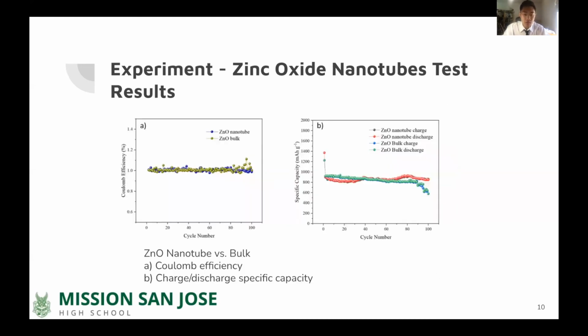Finally, in this figure, the nanotubes are a lot more stable than simple bulk zinc oxide. The bulk zinc oxide specific capacity is higher than the nanotubes for the first few cycles, as you can see in the figure. However, it steadily decreases until around cycle 80, where it starts to drastically decrease. The specific capacity for nanotube zinc oxide, however, is steady at 861 milliamp hours per gram. The initial Coulomb efficiency is obtained by dividing the charging specific capacity of the second cycle by the discharging specific capacity of the first cycle.